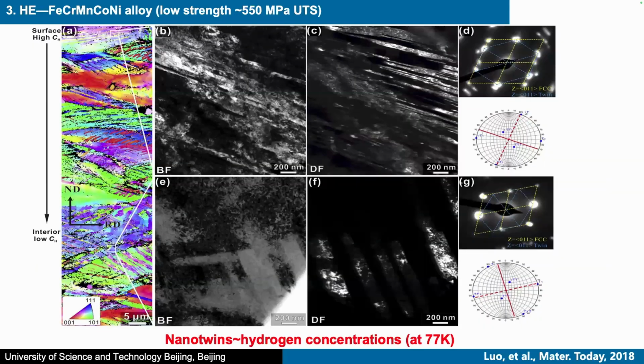Then we also did a similar experiment. The material was tested under liquid nitrogen to prevent cracking. We also found a relationship between the density of nanotwins and the hydrogen concentration.